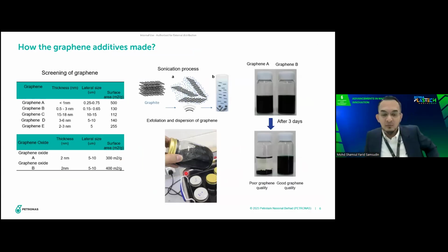And for the graphene additive, we have carried out a few approaches before producing this additive, in terms of selection of graphene and also in terms of the process. As you can see from this table, there are different types of graphene with different thickness and lateral size. So these are important parameters when we want to select the graphene to make it an additive. And from this, we can see we have different thickness of graphene, lateral size, and also surface area.